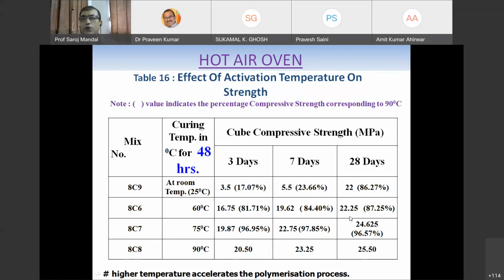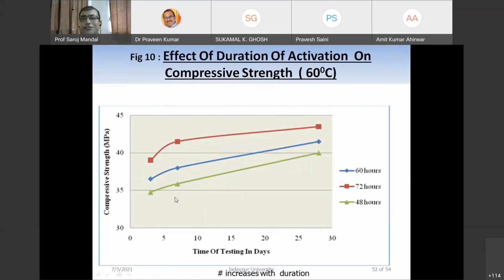So the temperature has a role, but you see that 60 degrees C we think is more appropriate because almost 80% of the strength has been reached. If you see this graphical picture, it will be more clear. Here it is the date of testing, that is our 48 hours. Now here is the effect of duration. Temperature is kept at 60 degrees C, and the durations are 48 hours, 60 hours and 72 hours. 72 hours gives the higher value, then 60 hours, then 48 hours. So if we increase the curing duration, you can get a higher strength at 28 days.